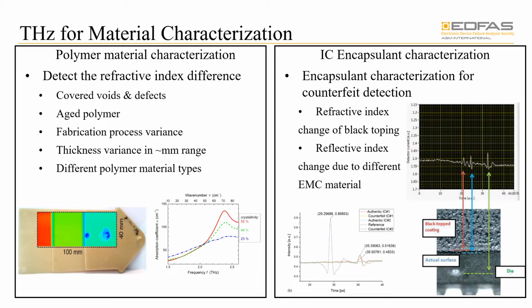So in this sample, we also see defects that have been detected, and these defects have been detected due to the differences in the refractive index of the air and the polymer material. Another thing to note is the polymer crystallinity, which will affect the terahertz signal absorption. This means that the terahertz is able to differentiate this polymer with different fabrication processes and aging. And since this process will overall affect the polymer crystallinity percentage, that means we can possibly use it for the detection of counterfeit samples, aged samples, reused samples, or even maliciously modified samples, which have gone through different material fabrication